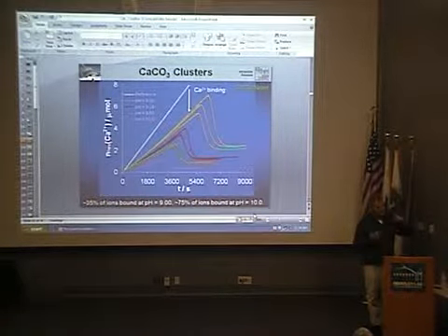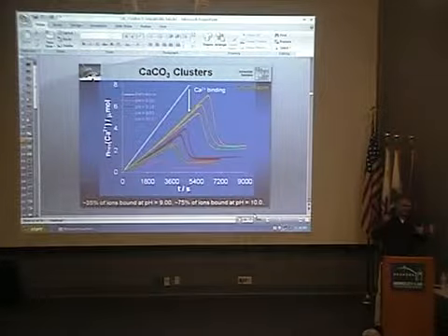So what I detect in the centrifuge is refractive index. So this is the sum of ions plus ion pairs plus clusters. And if I separate the clusters out, then I can only detect a refractive index. And if I assume the refractive index of the clusters being the same as the ions, otherwise I can't relate the concentrations, then I end up with this 1%. So this is the minor amount.